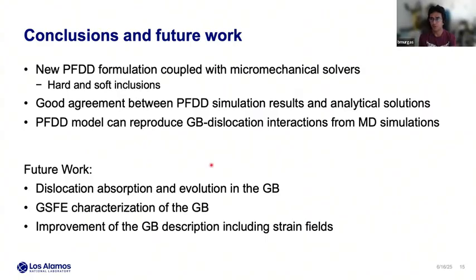I'm using a lattice energy that is proportional to the bulk energy, but we are also working on the gamma surface calculation of the grain boundary, which will give us a better description or definition of our grain boundary region. Finally, we can use a different methodology to define the grain boundary, by computing strain fields from MD and then using those strain fields as inputs in our phase field dislocation dynamics. I think something similar was done a couple of years ago. Another way, if you're curious, is to compute the grain boundary dislocations and use them as additional order parameters to describe your grain boundary, and we have done that too.